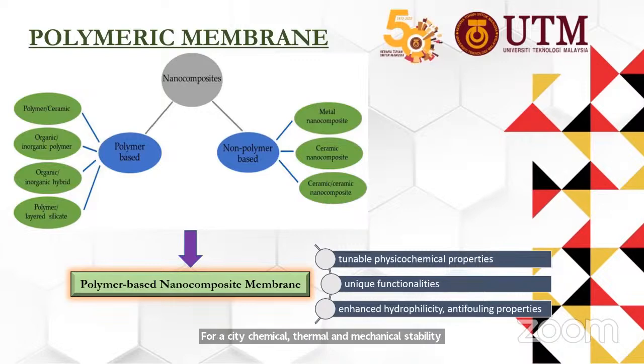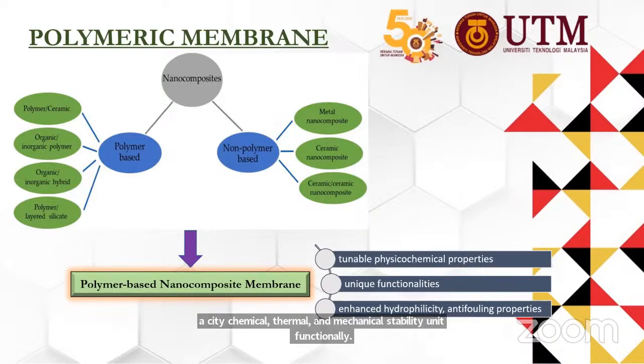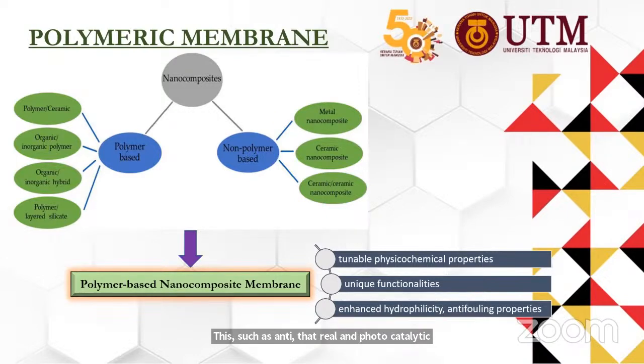Unique functionalities such as antibacterial and photocatalytic characteristics can be introduced to the membrane by incorporation of nanomaterials into the polymer. In addition, physical characteristics such as strength and modulus can be improved as a result of strong interfacial interaction between the nanoparticle and the surrounding polymer matrix. Nanofiller materials such as nanoclay, graphene oxide, carbon nanotube, cellulose nanofiber, and nanocellulose have gained particular interest in the water treatment community due to unique properties like high surface area, low cost, fast adsorption kinetics, thermal stability, chemical stability, and mechanical stability.